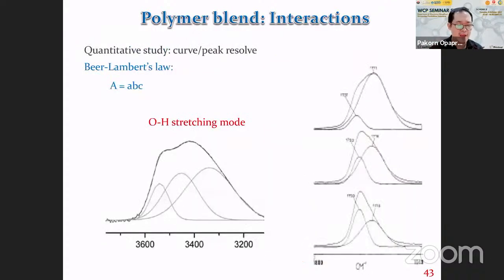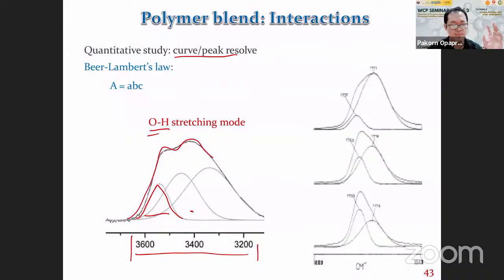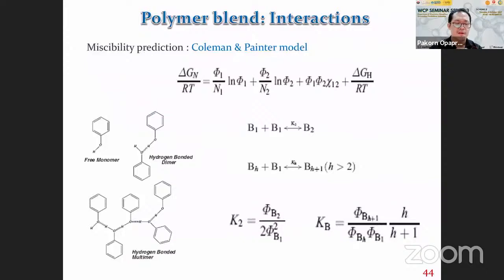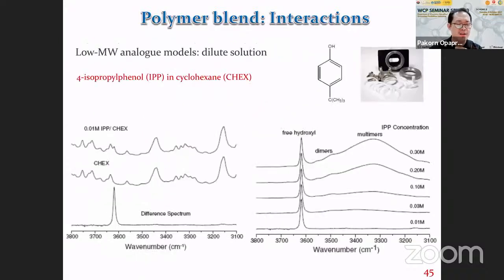How much? We can use what we call curve or peak resolve technique to get band area. So actually, this is OH stretching mode. You see very broad spectrum like this. It consists of so many peaks in here. So we can use a curve fitting technique to determine how many bands or how many peaks we have. So as a result from that, we can also study the nature of hydrogen bonding.